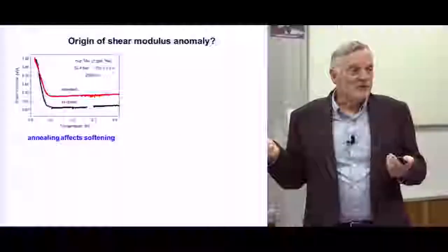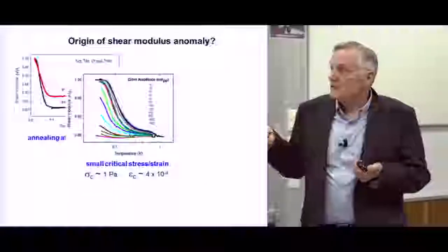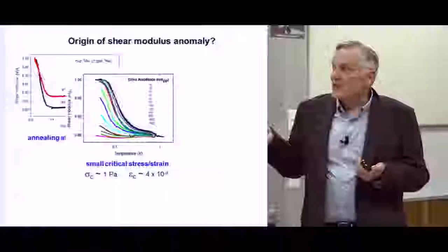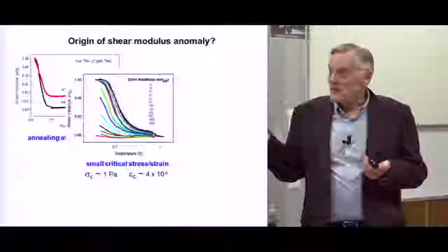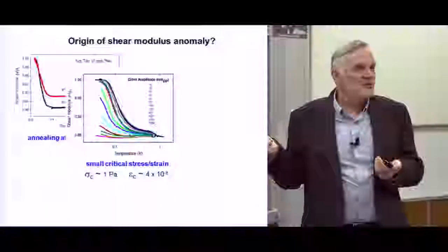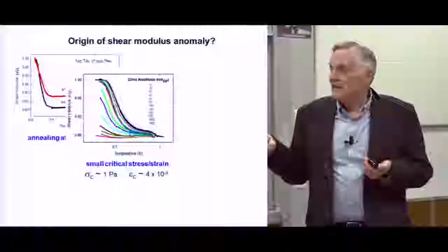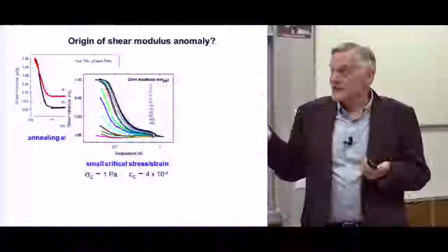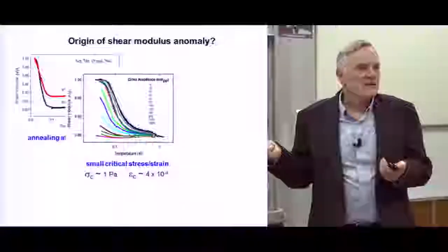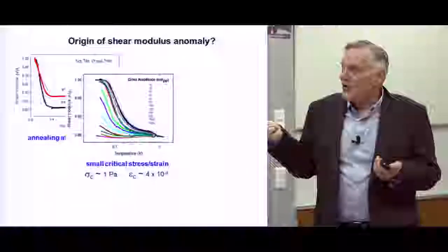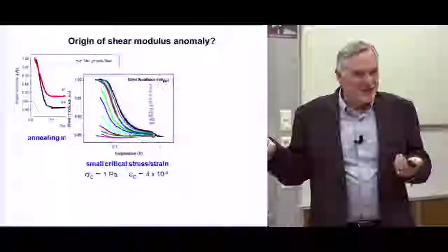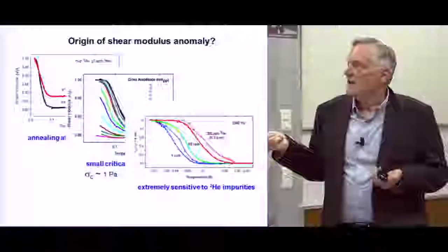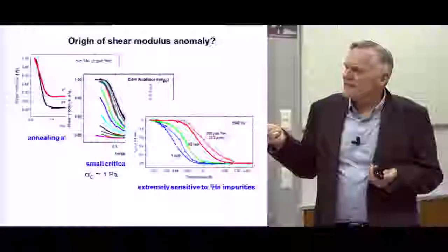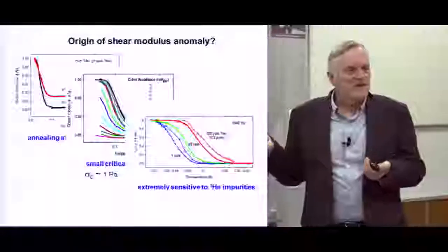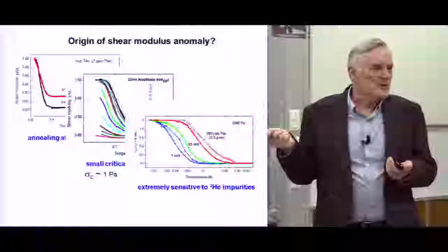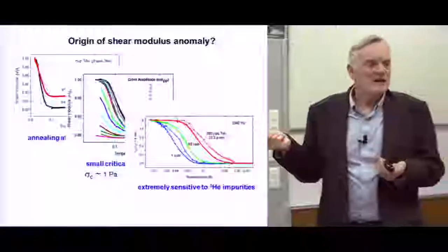And it does depend on how you treat the crystal. It also, and we knew this right away, is if you do this measurement at higher amplitude, it also goes away. It becomes soft at all temperatures if you do it at high amplitude, right? And not very high amplitude. The stresses required to suppress this are very small. This has to be a very gentle experiment to see the effect. Okay, so this also, even though it's a shear modulus effect, is going to make it look like a critical velocity. And finally, the temperature this happens at is very, very sensitive to a tiny amount of helium-3 impurity, which wasn't expected, but when we checked it for good luck, it turned out to be.